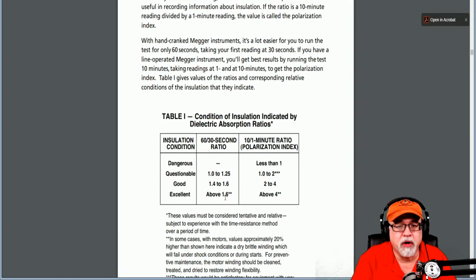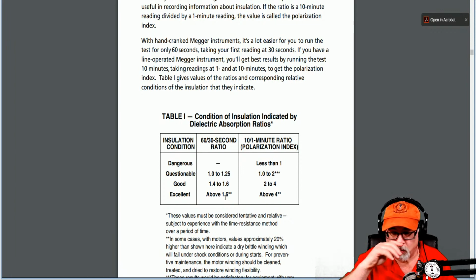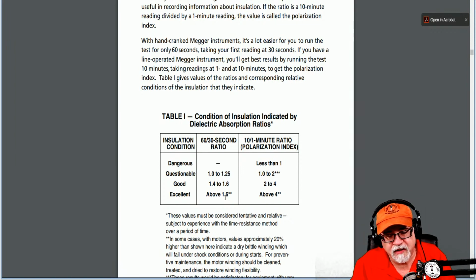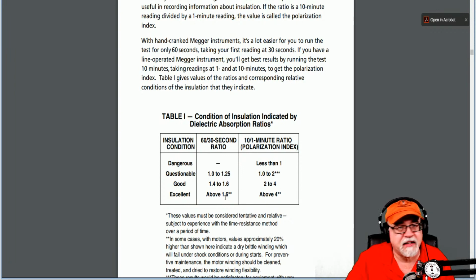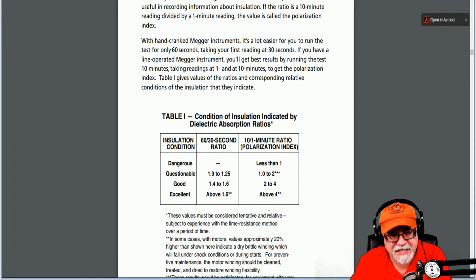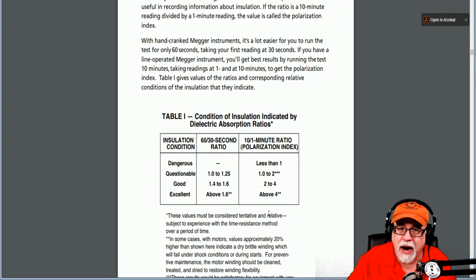It means that immediately we're going to jump to the 10 and 1. Since you're already taking those values anyway, we're going to jump to that. If you do a 10 and 1, it means I take the value that I got at the 60 seconds, and then I take the value I got at the 10 minutes, and I divide the 10 into 1, okay? That's going to give me what's called a polarization index. And again, if it's 1.0 or greater for wire and cable, then I'm telling you it's probably okay. Then you would just consult with your manufacturer. So ideally, we'd like to see 2 or greater in the polarization index, and we'd like to see at least 1.4 or greater in the 30 to 60 second absorption test. That does not mean that 1.0 is bad when it comes to wire and cable.